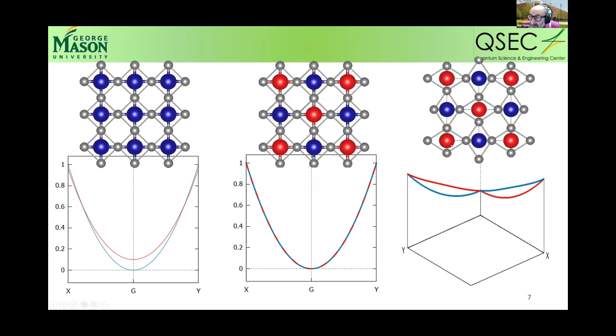And you can clearly see in this toy model how it works. Let's say we start from this red atom in the lower left corner. And let's say we proceed along the x-axis. So we go first along the long axis, then the short axis, then the long axis, and so on. If we go in the other direction, that will be a different dispersion because we start from short and then go long.